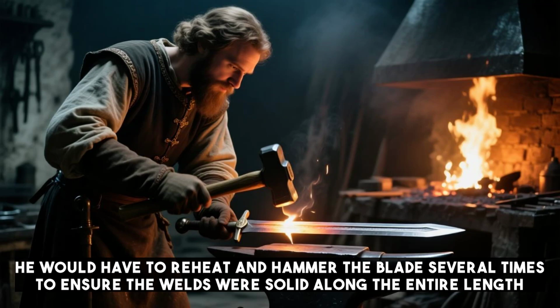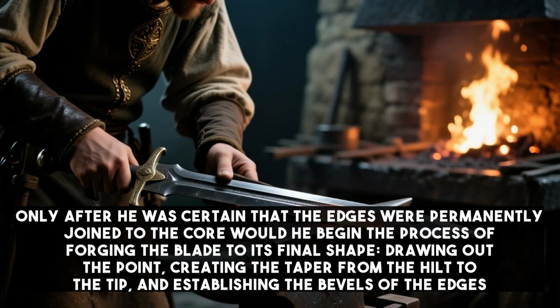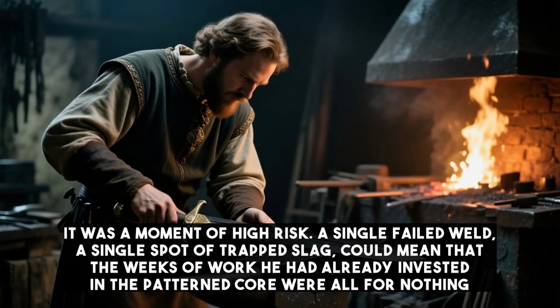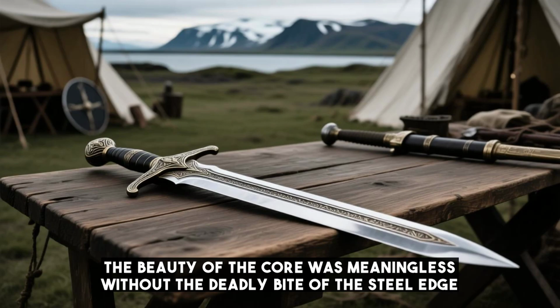He would have to reheat and hammer the blade several times to ensure the welds were solid along the entire length. Only after he was certain that the edges were permanently joined to the core would he begin the process of forging the blade to its final shape, drawing out the point, creating the taper from the hilt to the tip, and establishing the bevels of the edges. It was a moment of high risk. A single failed weld, a single spot of trapped slag, could mean that the weeks of work he had already invested in the patterned core were all for nothing. The beauty of the core was meaningless without the deadly bite of the steel edge.